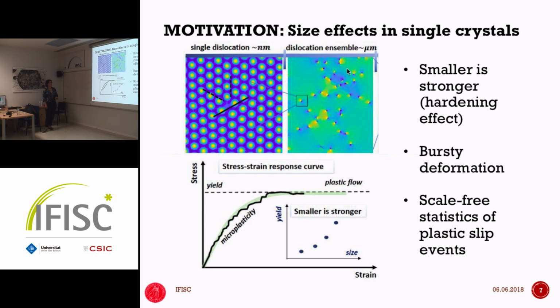So in particular, if we think about single crystals, then the kind of defects that we're looking at are these dislocations. Sometimes you can have a gas of dislocations, but the system is not sufficiently big for them to pile up into grain boundaries and break the crystal into subcrystals. So they are still like an interacting gas of particles. And in this case, the stress-strain curve has this signature that when we enter the nonlinear dissipative regime, the curve loses its smoothness. It becomes fluctuating, so there are strong fluctuations that appear in the response, and then eventually you get into the plastic flow regime. And these fluctuations, these bursts in the strain response, have power law distributions. They're broadly distributed. That means that all the local average approaches fail in this regime. You have to worry about correlations in the system, so you have to worry about non-local effects and how to put them into the theory.